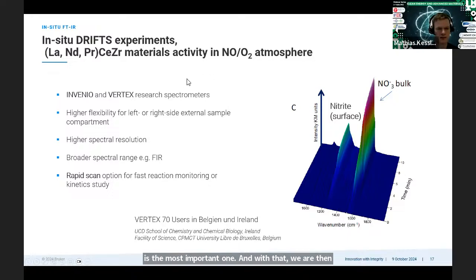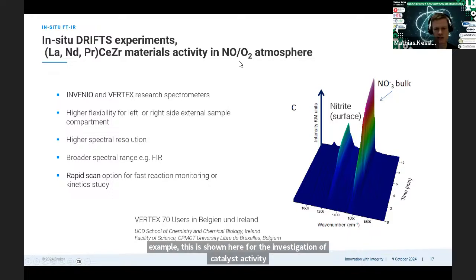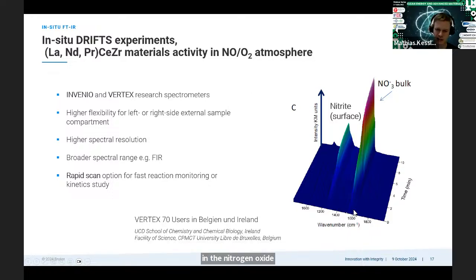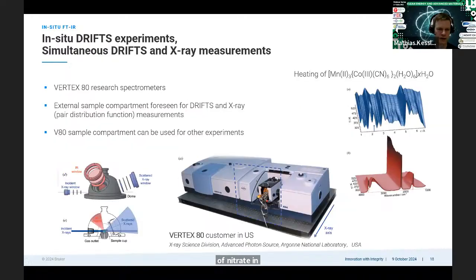And for example, this is shown here for the investigation of catalyst activity in a nitrogen oxide oxygen atmosphere. And then we see directly what is happening on the surface of the catalyst. And we see the formation of nitrite on the surface and also of nitrate in the bulk of the powder.